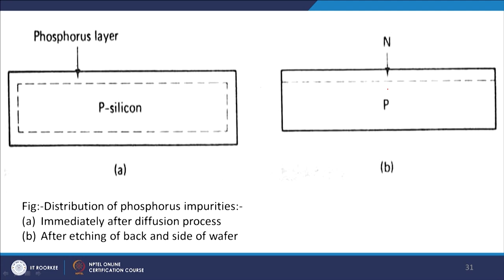When the chamber is heated, the phosphorus slowly diffuses inside and overrides the boron impurity to make a highly doped, narrow n-p junction. The diffusion process deposits phosphorus on all sides of the wafer. We need n-doping only on the top, so we must etch the bottom and side surfaces. After etching, we obtain n-type doping on the top and p-type doping at the bottom, giving us the p-n junction.